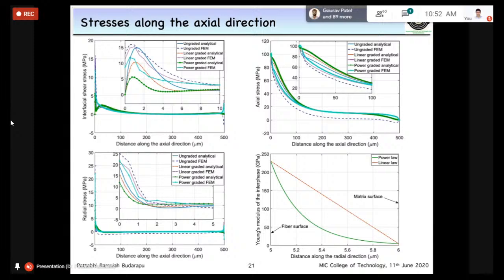There is an explanation for the power grading, because we see a significant drop in properties with respect to it. So we try to analyze the reasons, and we understand the distribution of the modulus in case of power law as well as linear law shown in the fourth picture. The power law is the green line, and the linear law is the orange line. We see a sharp drop of properties within a small distance using power law.